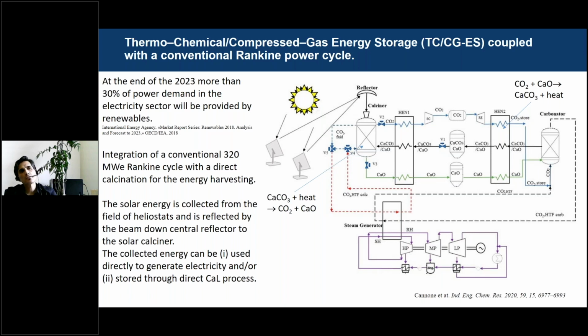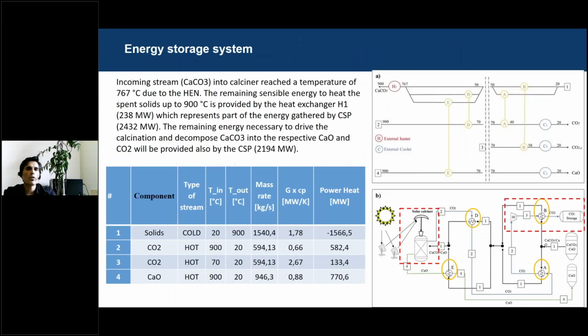And then these components can be reused in a carbonator in order to release the heat, and so to feed a classical Rankine cycle with high, medium, and low pressure. The energy storage system is composed of the calciner itself, but also of the compressor unit, which is able to store the CO2 in a supercritical phase. We have approached the integration, or say the recovery of the excess heat, with the help of the well-known pinch analysis.